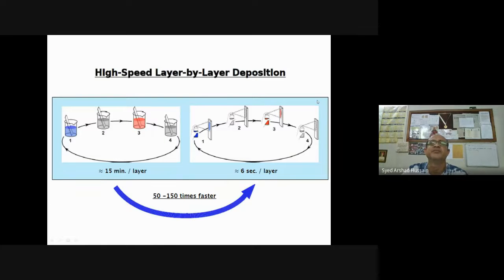So it's possible. Now people also tried with spraying. But in the process we described, you have to dip, you have to wait some time, and you have to optimize the time. On average, say 15 minutes, 20 minutes. How can you optimize it? Say you dip, wait, and in 1 minute you take out and measure, say, the absorption spectra. Then again you dip, take out after 5 minutes, and measure the absorption spectra. You will see the absorbance increasing.